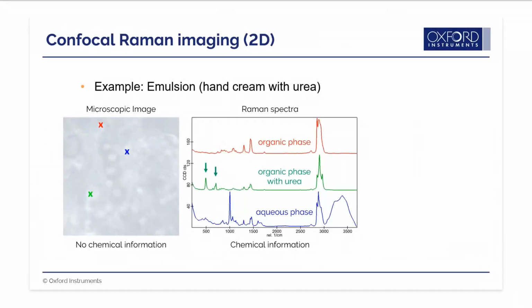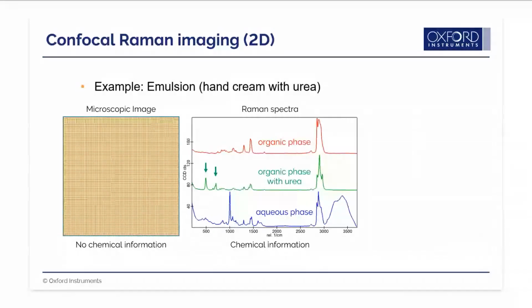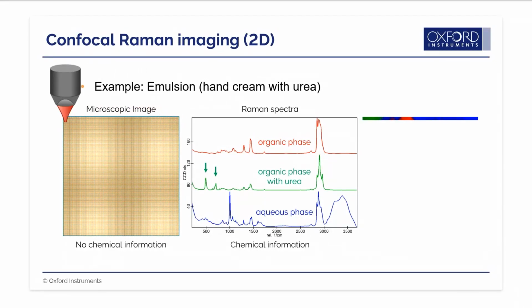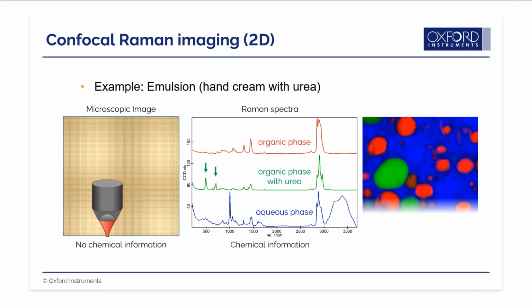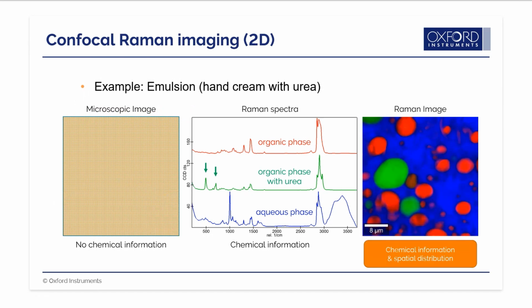To study the distribution of the urea containing phase, Raman imaging is required. This is done by defining the size of the measurement and the number of pixels that shall be measured, indicated here by the grid. The idea is to measure a full Raman spectrum at each pixel. Let's start the measurement. From the information in the Raman spectrum at each pixel, it is straightforward to create the Raman image that shows the distribution of the components.